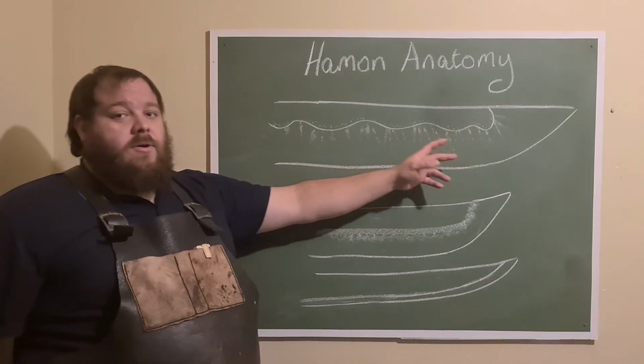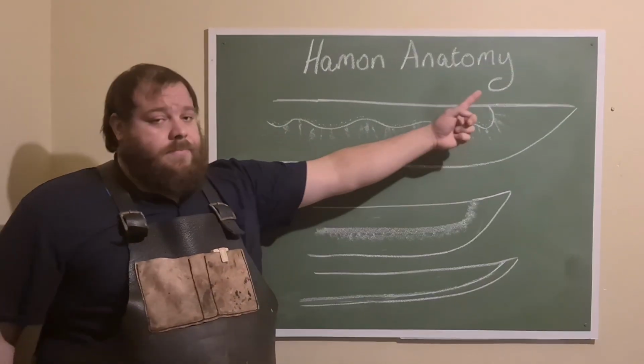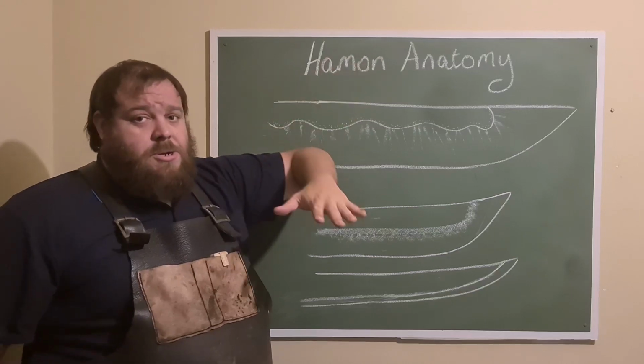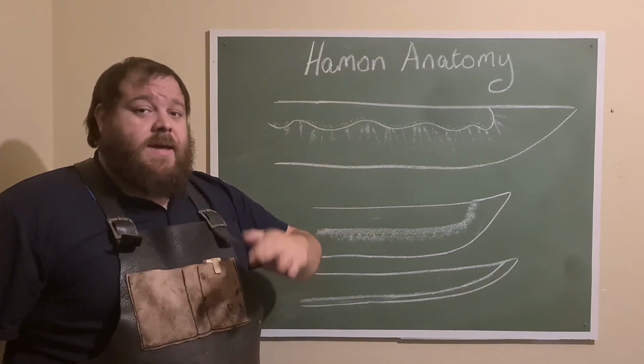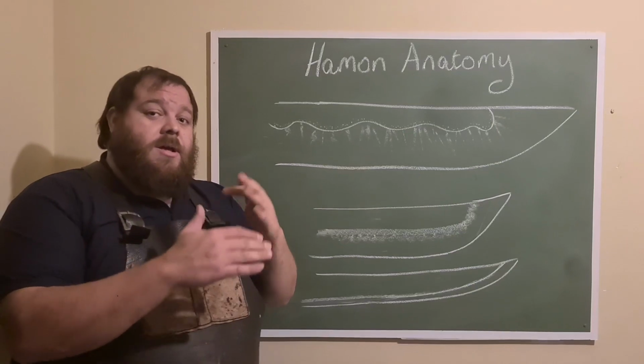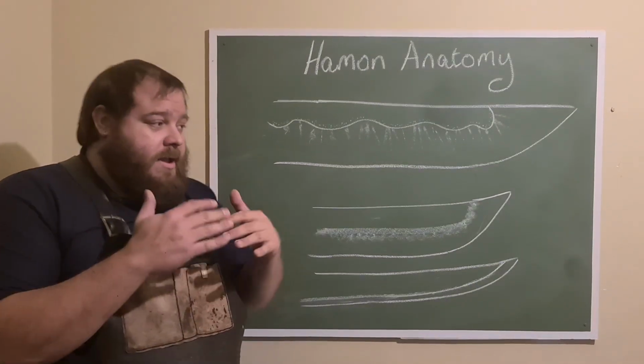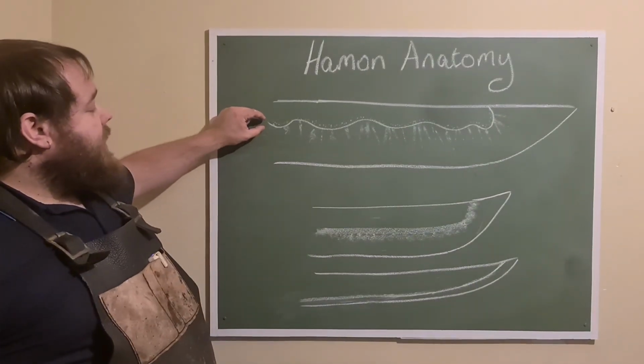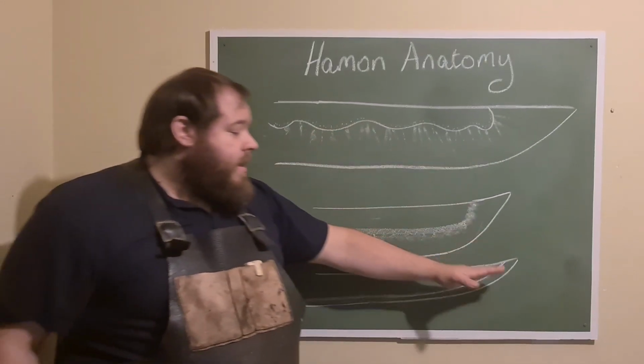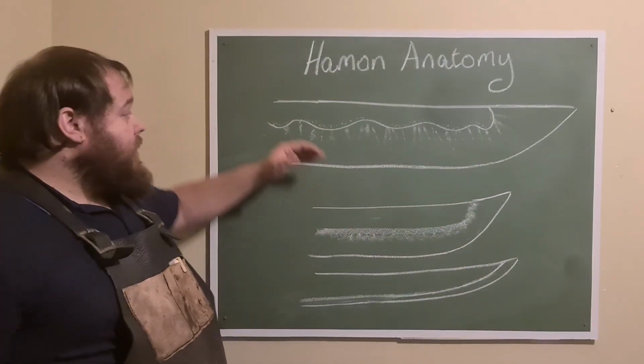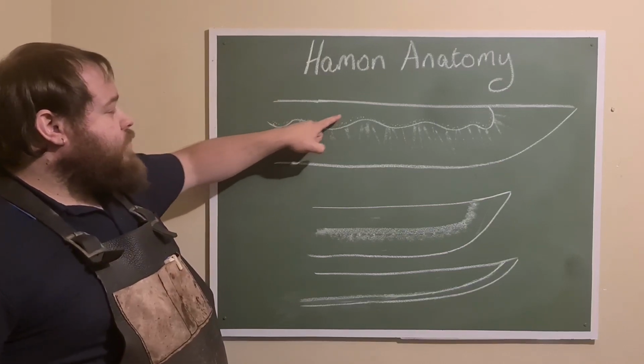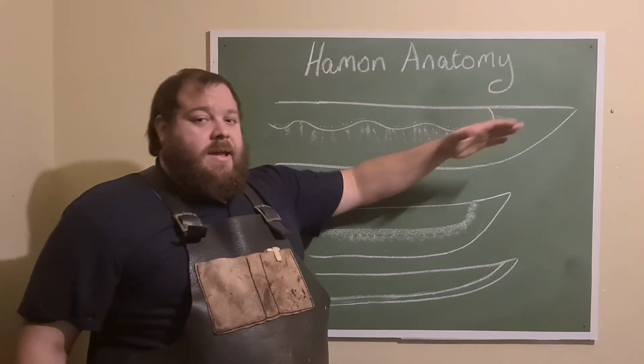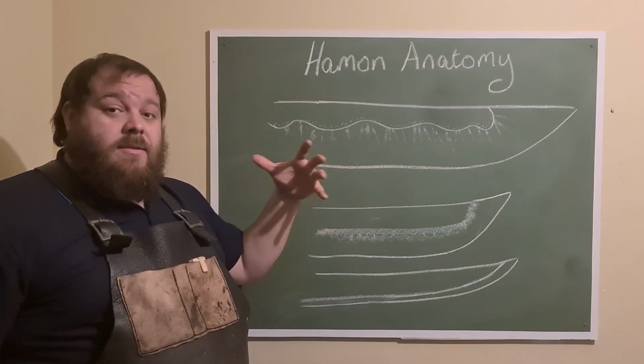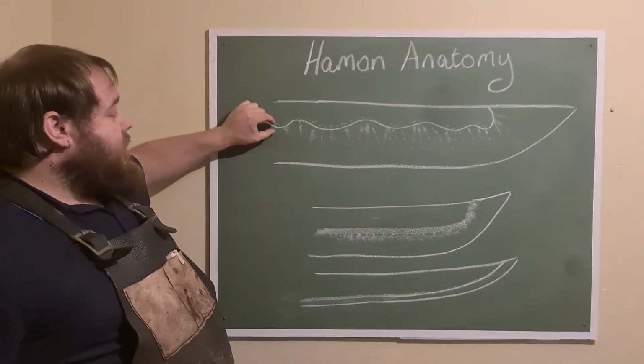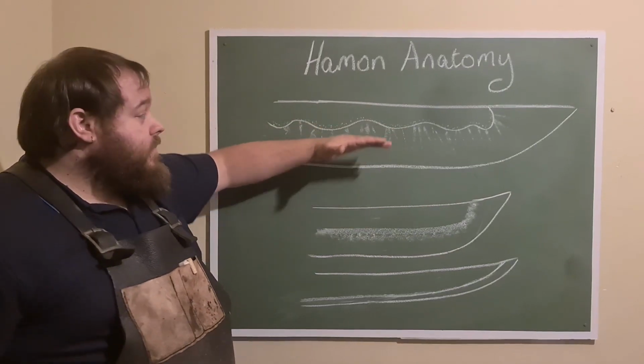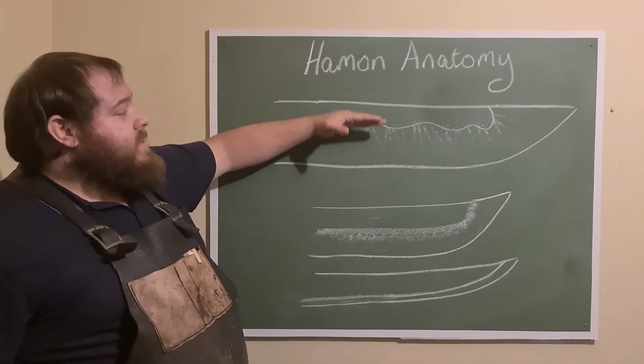And that's what normally creates that line in the steel. It is literally just a delineation where austenite is transforming into martensite, but hasn't quite yet. And so there's a mixture of ferrite and cementite and all that kind of stuff in the line. And that's why you'll see, even on the very hard-lined Hamon after etching, this almost sprinkle-dotted thing above the hardening line in the soft steel. And that is actually the gradient where you've gone from true hard steel into the softer material.